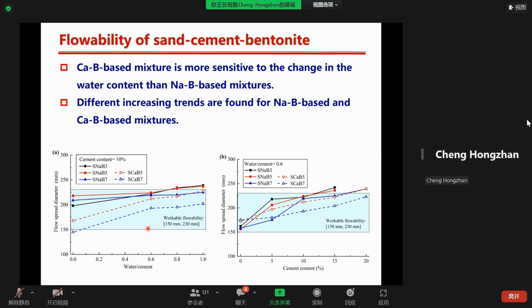Based on the left picture results, the calcium bentonite based mixture is more sensitive to the change of the water content than the sodium bentonite based mixtures, in agreement with the results in the first stage.